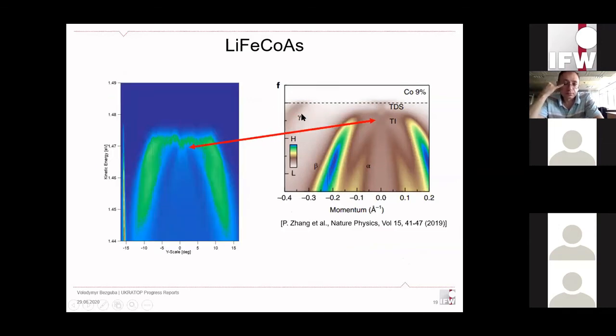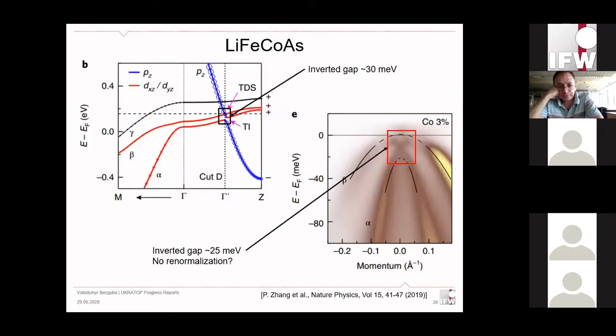That's because if we see such spectra even with laser, like I showed before, it does look similar to that. Though this is not even cobalt doped material, so the Fermi level is not shifted, it's just pure LiFeAs. And also, if we look closely at the size of the inverted gap they report in their calculations, it is expected to be on the scale of 30 meV. And in the experiment, they see the inverted gap of the size of 25 meV, which means no renormalization, basically. And that's also very strange because iron-based superconductors are famous to have strong renormalization, like I said before.